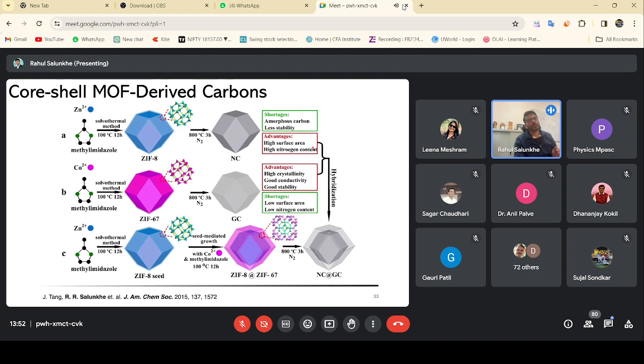Now we try to fuse these advantages into one material. We use ZIF-8 as a seed, and we try to coat it with the ZIF-67 material. And because of that coating, we got a nanoporous carbon inside and a graphitic carbon coated on the outside. So we try to fuse the advantages of these two types of carbons into one material by use of this work.